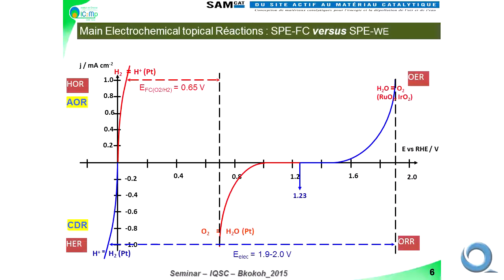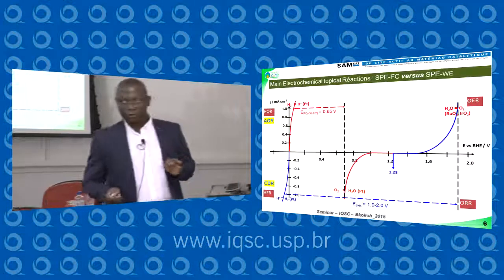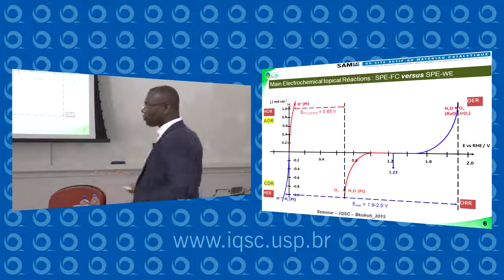If we consider this scheme, we have, for example, here, the possibility to prepare. We have here, for example, a hydrogen evolution reaction. And if we wanted to construct, for example, a fuel cell, we need the HOR. This means hydrogen oxidation reaction against the reduction of oxygen. As you can see here, for example, when you have a fuel cell and you increase the current density, you have the electromotive force around 0.65 volts. This is a good fuel cell.